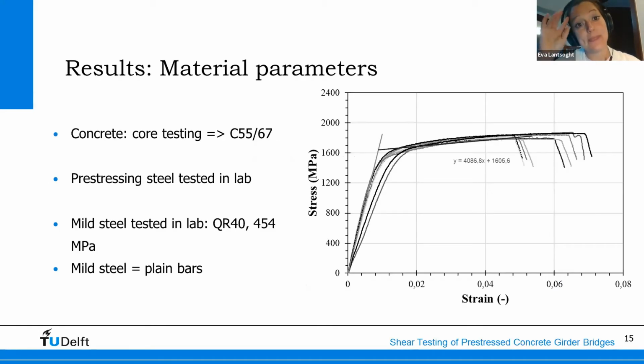We've done material testing to find the stress-strain relationships of the pre-stressing steel and the mild steel. And we did core testing to find the concrete compressive strength. So we know that we are dealing with a European concrete class C55/67. So that's a 55 megapascal characteristic strength when testing on cylinders, and 67 characteristic compressive strength when testing on cubes.